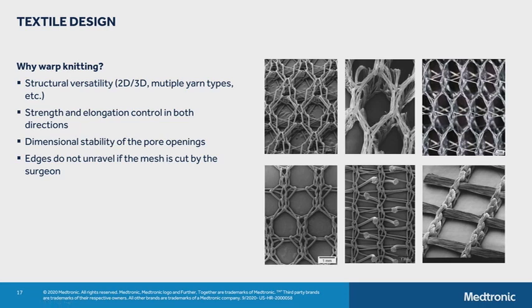We can control strength and elongation in both the warp and the weft direction. And we can create a variety of different pore sizes with these different geometries that are dimensionally stable. We can create gripped mesh. As you can see at the middle bottom picture right here, is an SEM micrograph, just to clarify. This has 2 different monofilaments in it. It has a polyester monofilament as well as a polylactide monofilament. The polylactide monofilament has been modified to create grips. So that is a pro-grip mesh that some people use. And lastly, one of the important advantages of warp knitting is that surgeons can cut the edge of the mesh without having to worry about it unraveling.